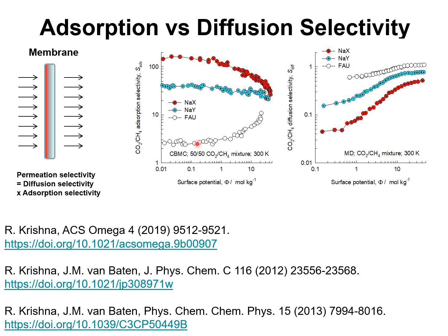However, the increase in the adsorption selectivity is at the expense of diffusion selectivity, and NaX zeolite has a diffusion selectivity of CO2 with respect to methane that is about 1 order of magnitude lower than that of all silica faujasite. The decrease in the diffusion selectivity is due to the fact that CO2 is much more strongly adsorbed, and is much less mobile than methane.